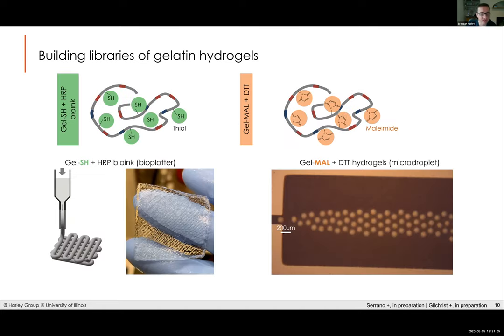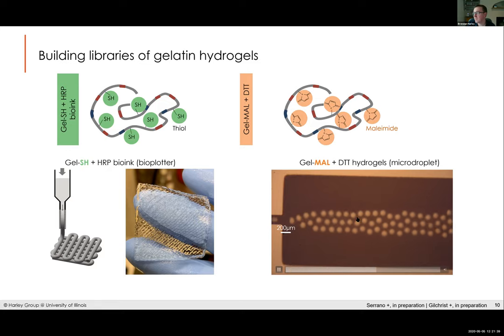We can use other chemistries as well. One example is using hyperbranched polyglycerols from Steve Zimmerman's group at UIUC, where we use methacrylate groups to crosslink polyglycerols into our biomaterial, then use thiol-ene chemistries to pattern growth factors or other things into the material. We also have a gelatin variation with a thiol group on the backbone that can be run through a bioplotter to 3D print these inks using enzymatic crosslinking. We've also created maleimide-functionalized gelatin backbones for rapid crosslinking, allowing us to create micro droplets 50 to 100 microns in diameter to encapsulate single cells.